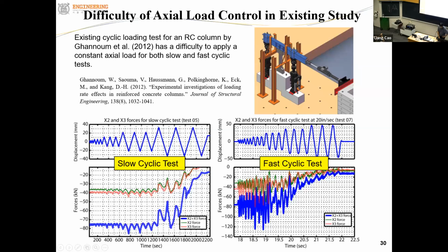That's the lateral displacement history for the slow test and for the fast cyclic test. And this shows the controlled force, or measured actual force. The blue line here is the final measured actual force for the slow cyclic test and for the fast cyclic test. You can see the large error. It is supposed to be a flat line, constant actual force, but you can see the large fluctuation here, even for the slow cyclic test. That clearly demonstrates the difficulty of controlling the actual force by using the existing force control method.